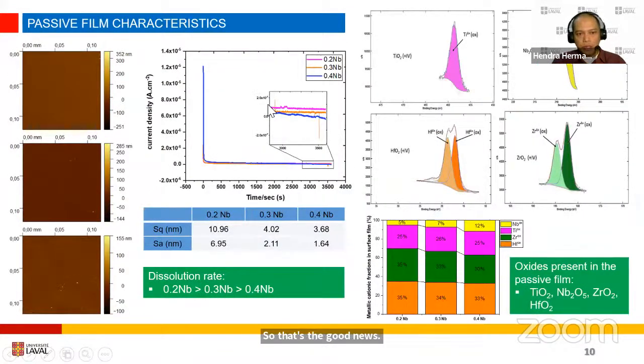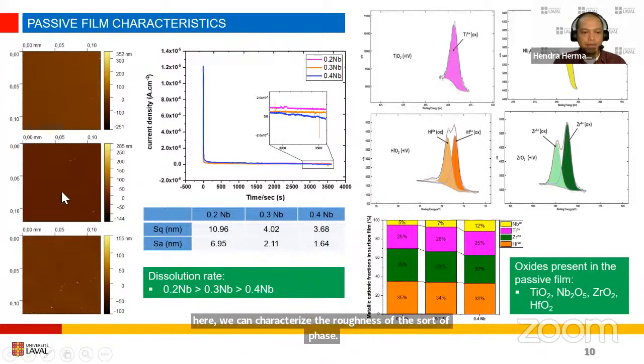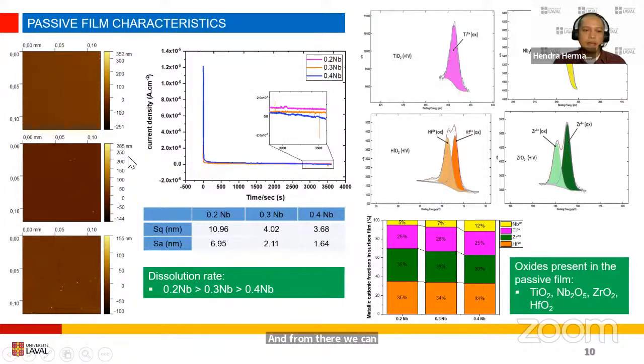And then we continued our characterization using AFM. This is some images obtained from the AFM. From here, we can characterize the roughness of the surface, and from that we can get some analysis on the dissolution rate. So based on these AFM images, we see that with the increase of niobium content, the dissolution rate decreases.